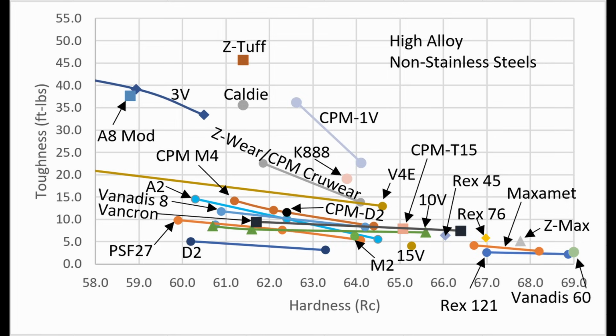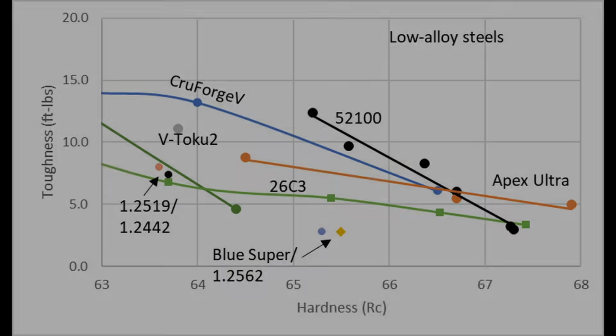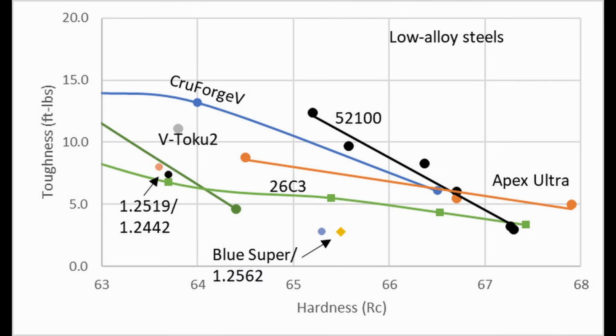So maybe there are certain edges that benefit more from toughness than from hardness, and so this type of regime would be better with a bit lower hardness but significantly higher toughness. Now, could we go even higher in hardness than 64 and maintain high toughness? That becomes more difficult. Maybe we could design a steel specifically to optimize toughness at 65 or 66 or 67 Rockwell, or a steel like my Apex Ultra maintains pretty decent toughness at 67 plus Rockwell.